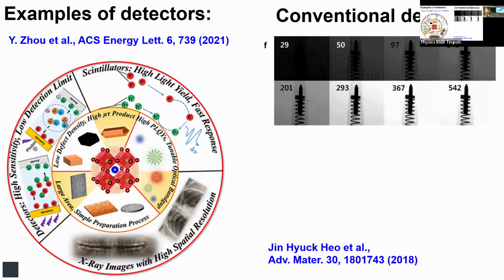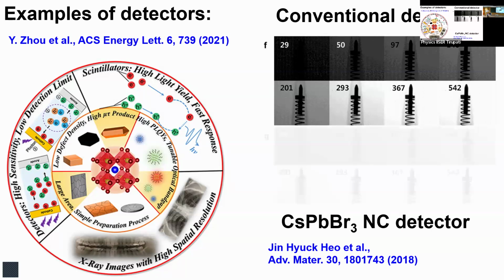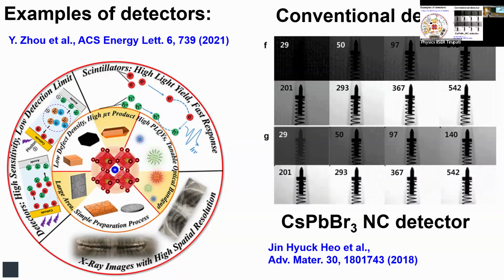The traditional X-ray photon detector is shown over here. This is in some units measuring the amount of X-ray I'm exposing. I'm trying to detect or image a pen. When I expose only this many X-ray photons, you see that I don't see any image at all, and the detector cannot detect anything. I get up to about 200 or so, get nice, good images. Here also the clarity is not good. With the traditional detector, but if I use CsPbBr3, then you can see that even at 29, you begin to see with much better clarity. So you can really reduce by almost an order of magnitude the photons that you need in order to get a clear-cut, high-resolution image with which the diagnosis can be done.